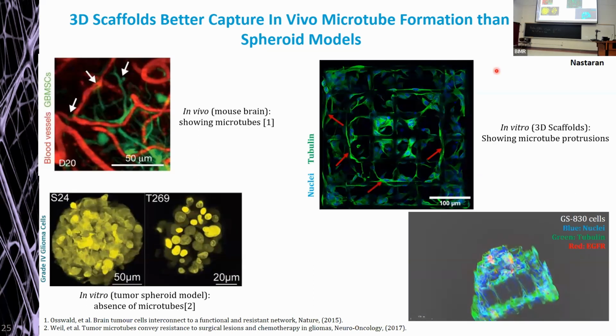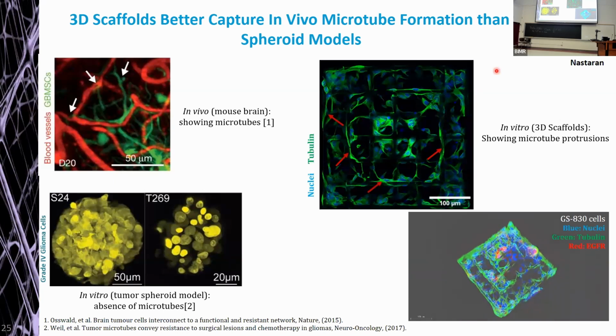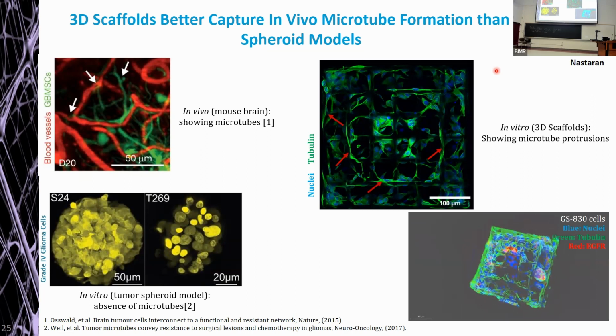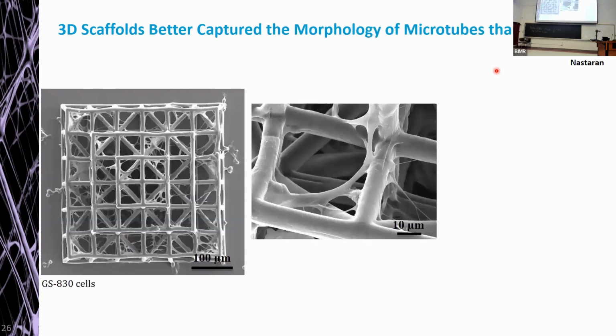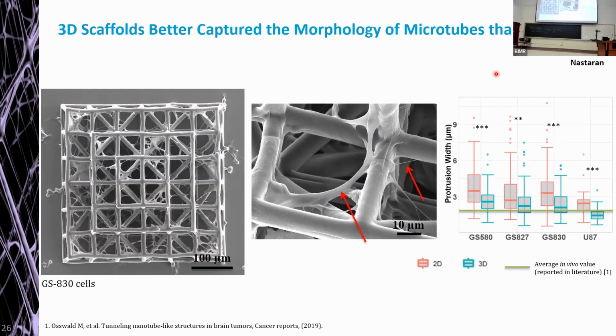Using our model, we were able to spot several of these microtubes, which were analyzed both by using immunofluorescence microscopy, but also using a scanning electron microscopy, where in particular, we could easily identify the presence of both micro and even nanotubes, as you can see here. And again, like for the nuclear area, the quantitative characterization, in this case, for what concerns the protrusion width, which, as you can see, in the 3D model is lower on average than the 2D model, and again, in line with previously reported values of microtube protrusions for cells in vivo.